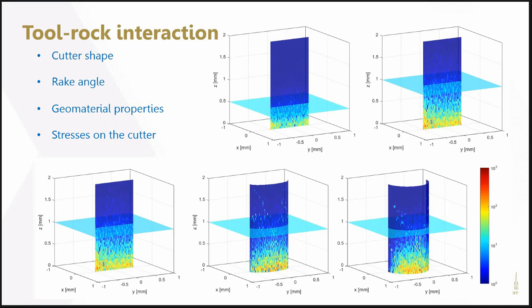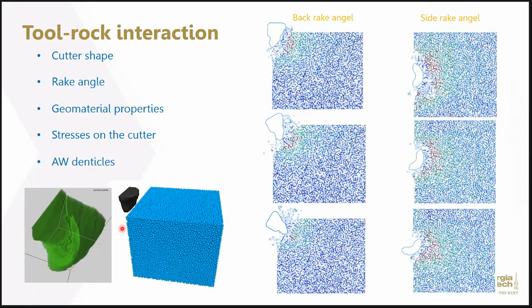And the curved surface has very similar, or identical, results. We actually plug in the denticle shape and do the simulation. We also look at the rake angle, the back rake angle, as well as the side rake angle, and how that impacts the results. Most of the results we obtained for the denticle cases are very similar to those of the half-circle cutter. So whatever benefits we saw earlier in terms of half-circle cutter versus a plate cutter are applicable to the denticles of the angelwing here.